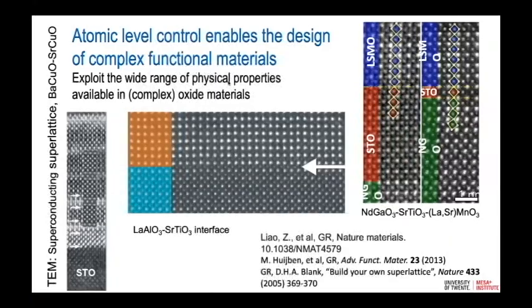Just to give you a few examples, these are cross-section electron microscopy images from very early work, more than 20 years ago. On the left is a cross-section of a superlattice of superconducting materials. In the middle, this is an interface between two perovskite materials where we induce a two-dimensional electron gas. And on the right-hand side, you see a structure where we were able to control the magnetic properties.